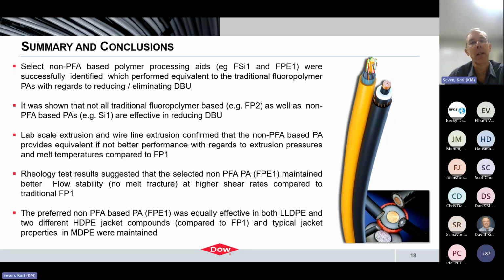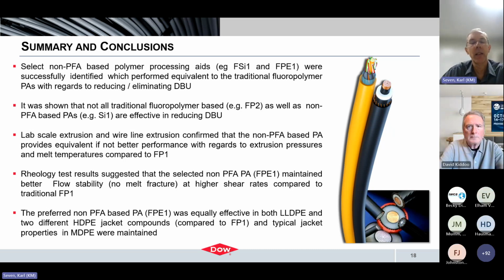Rheology tests showed about similar performance versus the typical fluoropolymer processing aid, and even going into full-scale wire extrusion processing, we achieve about similar processing performance at that scale as well. We also extended this testing to linear low as well as high density jacketing compounds, and we're able to show the same benefit that we saw with medium density jacketing compounds. That's pretty much what I have here. I guess we can stop here and open up to questions at this point.